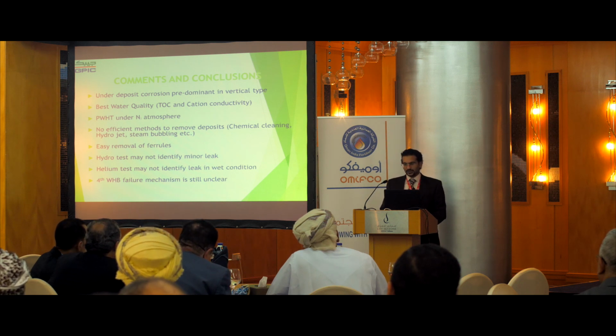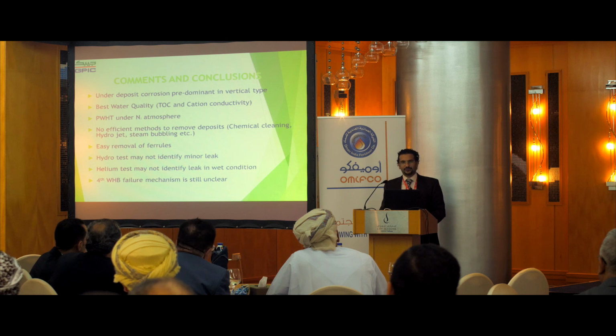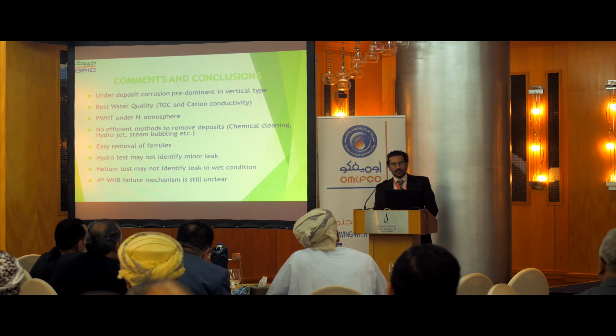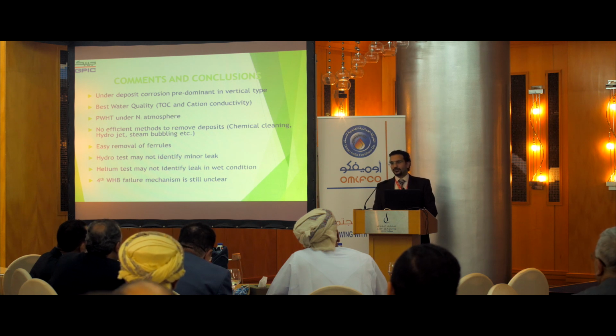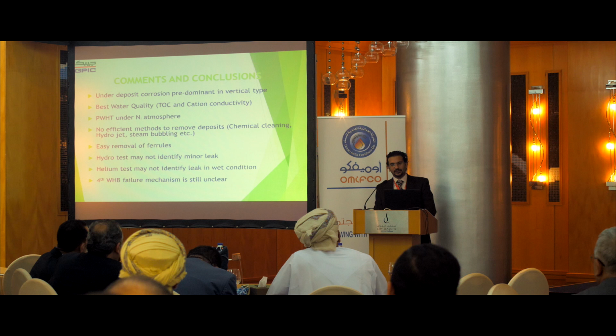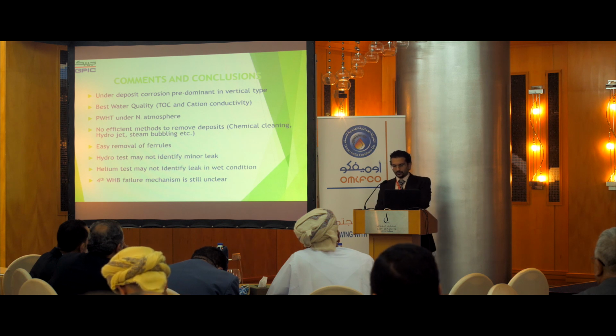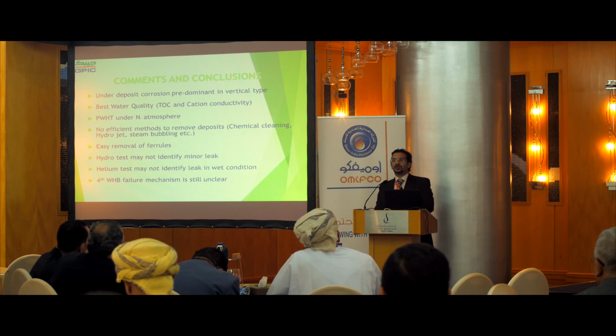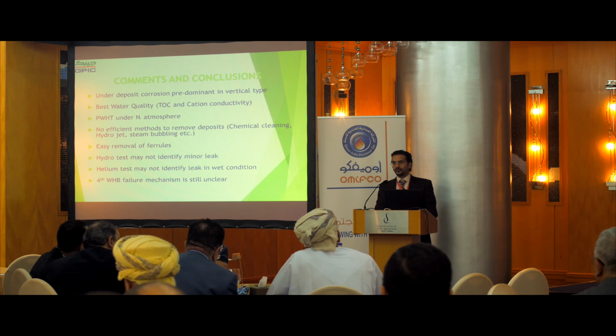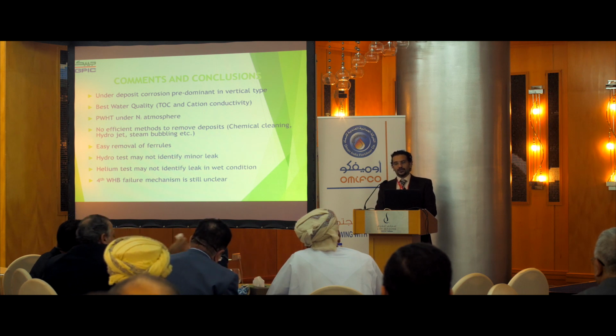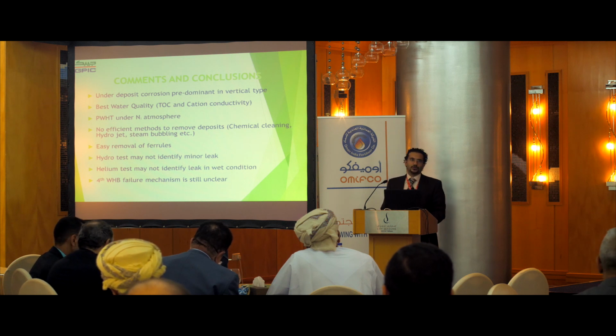The hydro test may not identify any minor leak that is there, hairline or less. And also, same as the helium test. Our fourth waste heat boiler, within 6 months, it failed, and we are still investigating that issue with the manufacturer. And we have gone to several meetings. We have cut out the tubes, the main tube that leaked, and another fresh, not affected tube. So it is still under investigation with them.